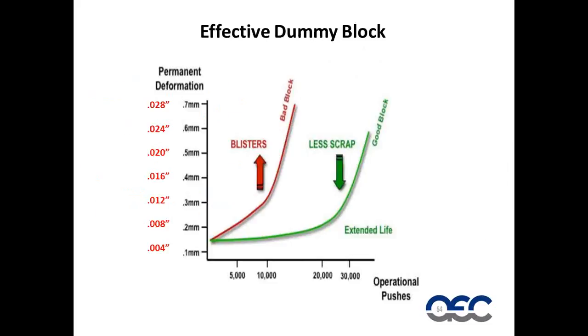This is a graph I've been using for many years, and every dummy block has deformation. If we make a dummy block at a given size, after the first couple of pushes, it will deform permanently somewhere between 4 to 8 thousandths of an inch on diameter. What we hope to do when we manufacture dummy blocks is to limit the amount of deformation for the longest amount of time. A poor dummy block will start deforming very, very quickly.